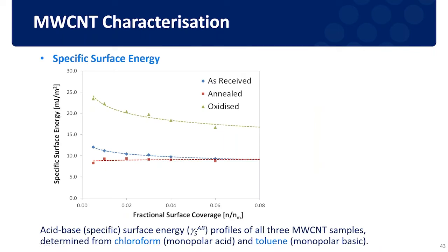And then we also measure the specific surface energy, which confirms the introduction of the additional oxygen-containing polar groups for the oxidized sample. So we have the highest specific surface energy for the oxidized sample compared to the as-received sample and the annealed sample. And the acid-base surface energy is clearly raised in the oxidized sample, and the surface energy distribution is clearly more heterogeneous also in comparison to the more homogeneous as-received and annealed carbon nanotube samples.